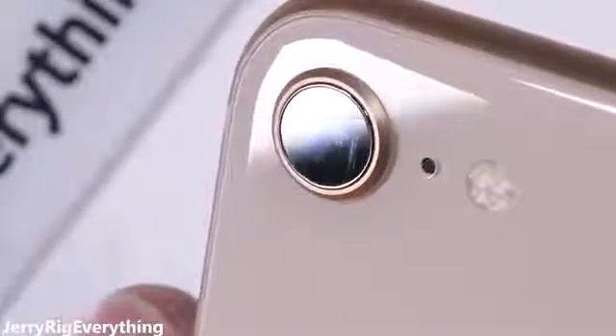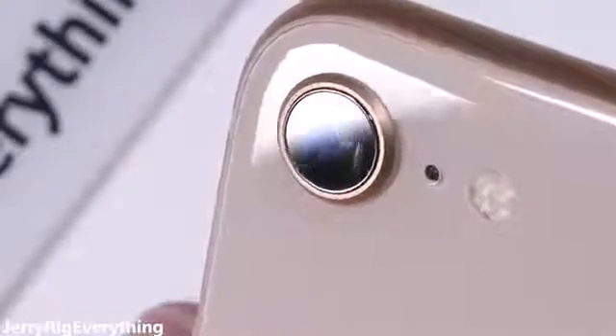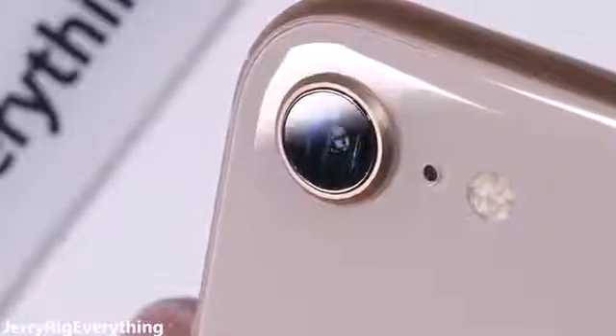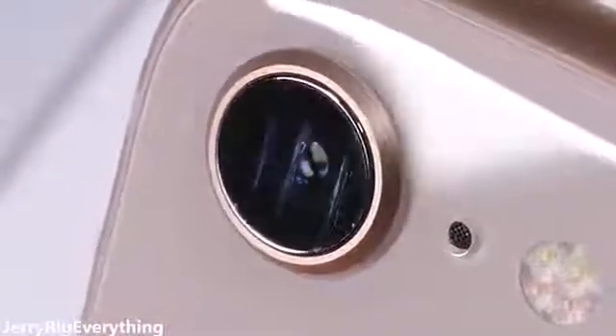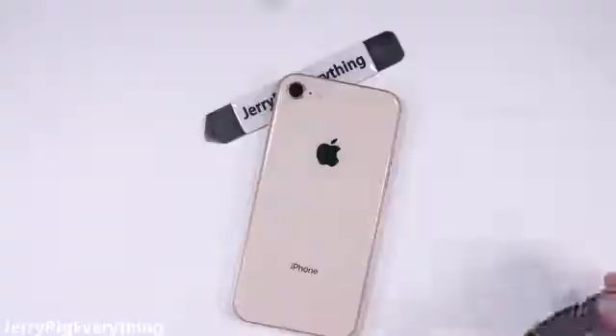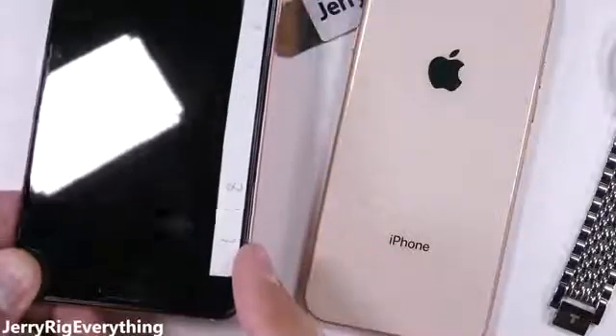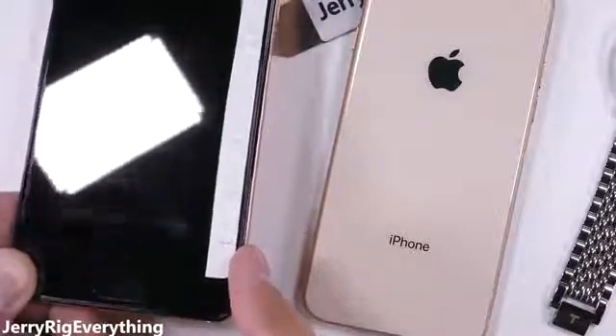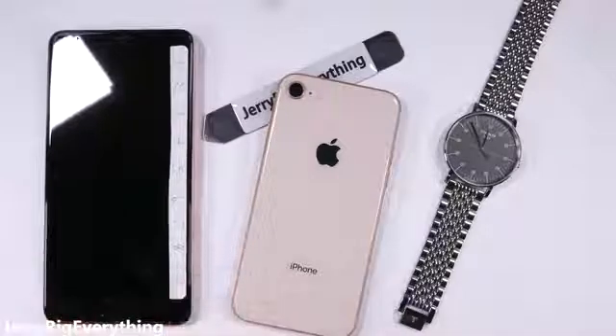It looks like Apple's still using their own proprietary blend of sapphire. I delved pretty deep into this subject during a previous video, and it is indeed aluminum oxide, which is the ingredient of sapphire, but my Mohs picks and an electron microscope indicate that it is a lower grade material than the actual pure sapphire that's used in Tissot's premium high-end watches or the full sapphire display on the HTC Ultra Sapphire Edition, both of which didn't scratch until level 8. Apple might have extreme attention to detail, but it's my opinion that they cut some corners with this sapphire stuff.